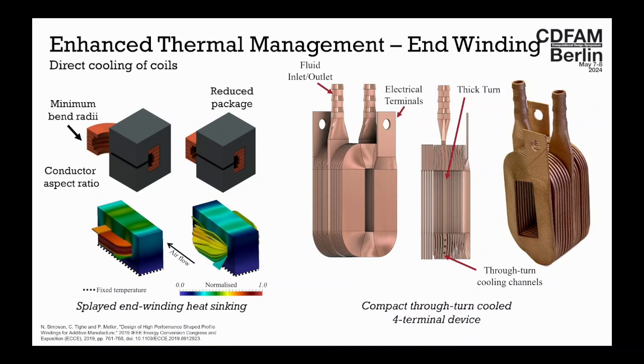Now, in winding design, unfortunately, you end up with a temperature gradient because you end up with more loss here toward the rotor than you do at the back iron here. And so being able to choose exactly where those cooling channels go is really valuable because it means that you're minimizing your head loss, so the amount of pressure drop that you've got in your system, and you're targeting exactly where you're putting your heating structure.